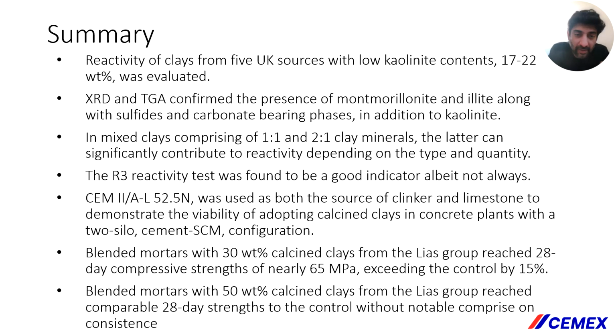Okay, to summarize then, the reactivity of clays from 5 distinct sources with low kaolinite contents between 17 to 22% was evaluated. TGA and XRD data confirmed the presence of montmorillonite, illite, along with sulfides and carbonates, in addition to kaolinite. It's clear that in mixed clays comprising both 1:1 and 2:1 clay minerals, the latter can significantly contribute to reactivity depending on the type and quantity. We found that the R3 reactivity test was a good indicator, albeit not always.